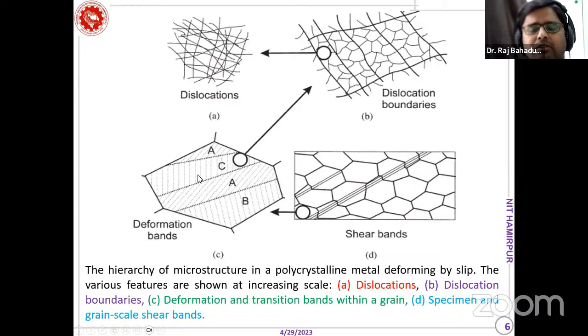And within a grain, if you see, then deformation bands are there. Within a grain, you will see different orientations. Then these are called deformation bands. And if you try to focus on a particular deformation band, you will find this kind of dislocation structure, and we can call them a substructure in the material. And finally, if you look closely after severe deformation, then the dislocation structure is there.